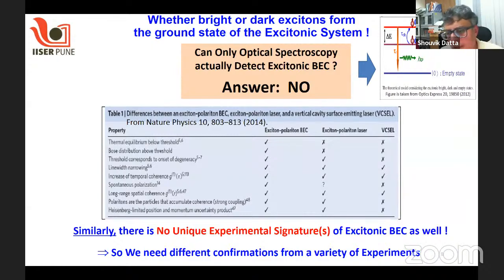Obviously, there are various reports on excitonic Bose-Einstein condensation. However, there is no unique experimental signature of excitonic BEC. People study various things to be able to say that, well, their material and structure is possibly undergoing this kind of phase transition. And we started asking the question: can optical spectroscopy alone actually directly detect excitonic BEC? Because in many semiconductors, like 3-5 semiconductors, the ground state, based on the spin selection rule, can actually be optically dark, and will not necessarily show any signature in light emission from these structures.